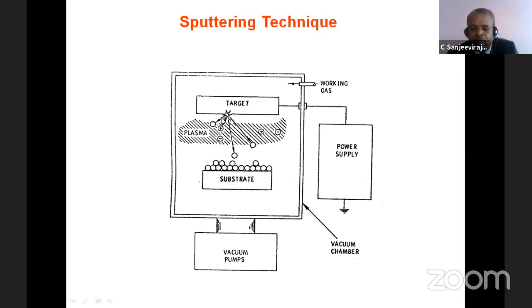Because of the bombardment, the argon ion is a very heavy ion, and it has a velocity also. Because of that, it has a very high kinetic energy, and that kinetic energy is more than the binding energy of the material to be vaporized or prepared as a nanomaterial. Therefore, when argon is bombarded, we can mechanically remove atoms. For example, if you take a tungsten target, tungsten atoms will be removed from the target. Or if you take tungsten oxide, molecules will be removed from the surface. So either atoms or molecules will be released from the target, and these will be deposited on your substrate.